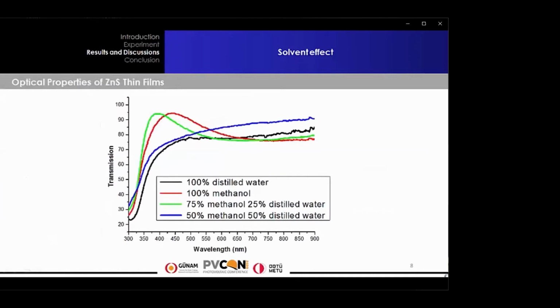The transmission spectra for the prepared layers are shown in the figure. The general shape of the spectra is similar. We can distinguish two transmission domains depending on the wavelength. A domain characterized by high absorption and low transmission of light radiation, which corresponds to wavelengths less than 400 nanometers. A high transparency domain located between 400 and 900 nanometers, in which the transmission takes values between 70 and 90%.